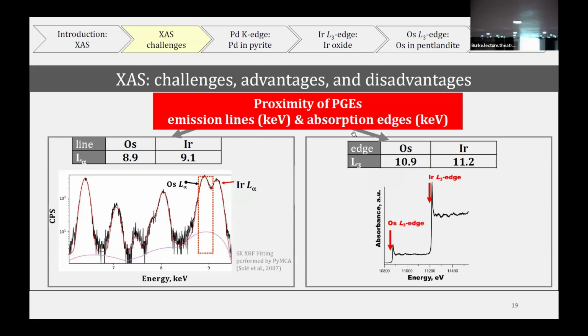Where can it lead us? Well, here is an example. This is a sample containing both osmium and iridium, and we chose the region of interest here. Instead of having a nice long XAS spectrum with a full EXAFS, we are getting the edge of iridium, unfortunately. So we are cutting part of the osmium signal. It's possible to overcome this problem theoretically or experimentally, but with the platinum group elements, it's always something to be concerned about.